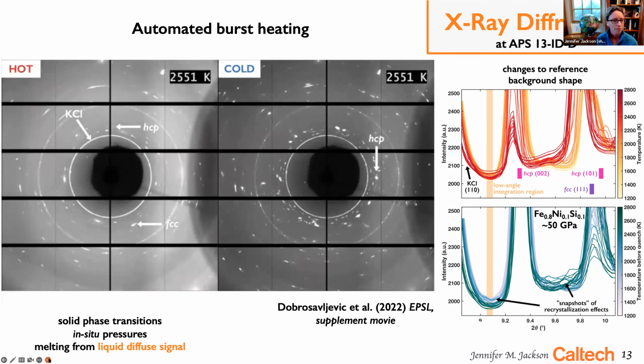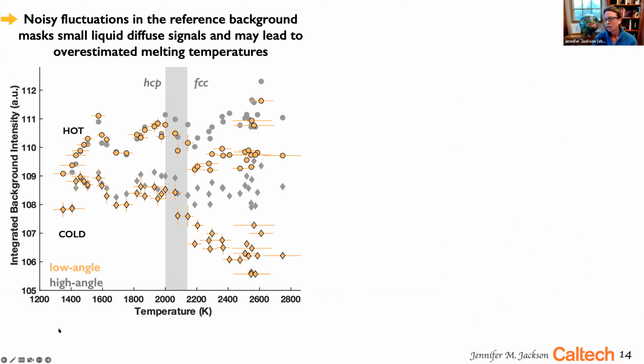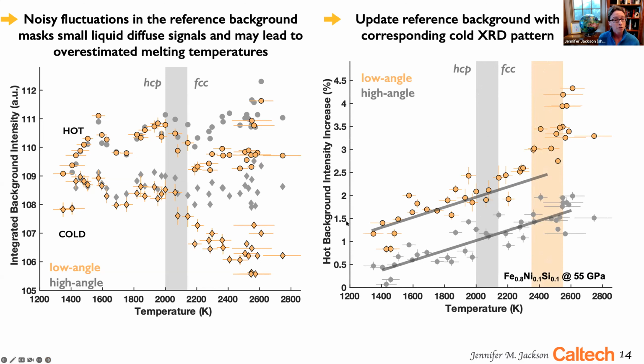This can create some challenges, because noisy fluctuations in the reference background can often mask small liquid diffuse scattering signals and may lead to an overestimated melting temperature. So what we do is update the reference background using the burst heating mode with a corresponding cold XRD pattern. In doing so, we can see a clear indication of where that signal starts to rise above the background, and it becomes much more obvious.